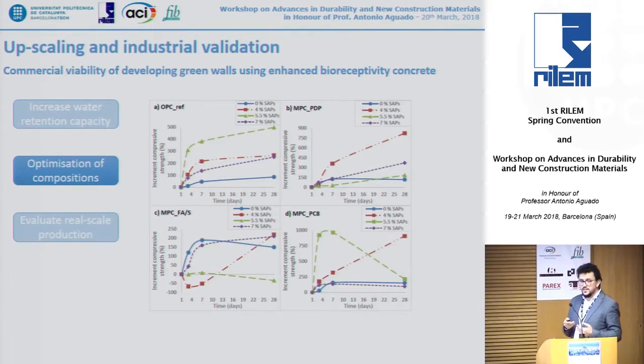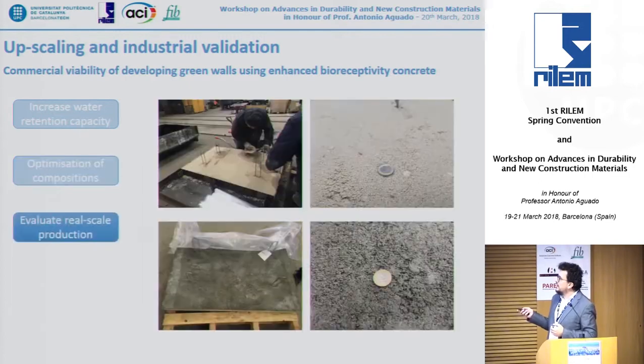The other thing that we changed: in much of the literature, you can see the use of ammonium phosphate in order to make the mix of magnesium phosphates. But the fact is, when using ammonium phosphate as the source of phosphate, you will have ammonium release in your medium, so it's not very acceptable for an industrial company to have ammonium released. So at this moment we are using another source of phosphates in order to meet the security requirements.